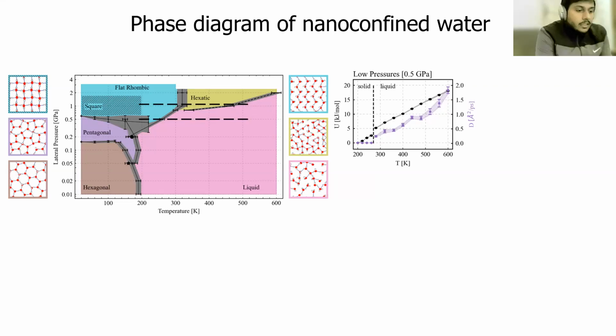In 2D, if a solid goes to a liquid, it could go via a so-called hexatic phase. Just like a liquid phase can be seen as an intermediate between a solid and the gas, a hexatic phase is an intermediate between a solid and a liquid, and it is known. Using pen and paper, you can show that a 2D system with a short-range potential should have a so-called hexatic phase.